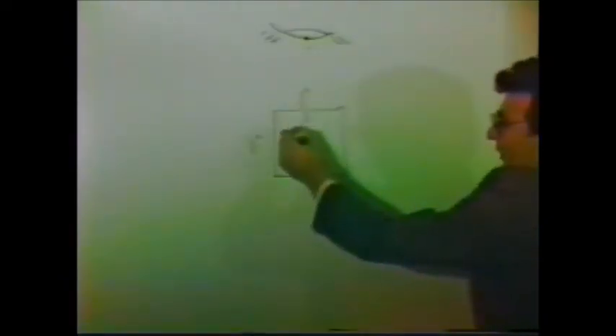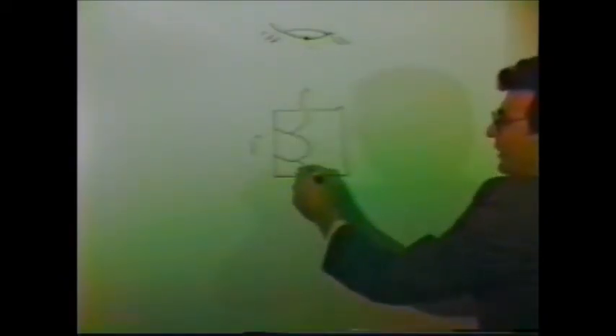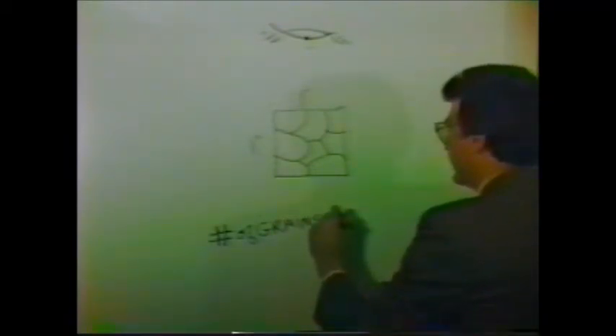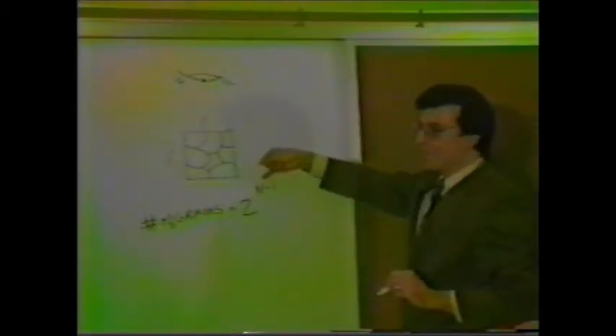And what you do is you count the number of grains that are in an average 1 square inch area viewed at 100x, and you count them. And you plug them into a formula, which is as follows. The number of grains is equal to this formula, 2 to the n minus 1. Now, what does that mean? This number n is the grain size that's reported, and we'll talk about that in a second. Let's just take an example.